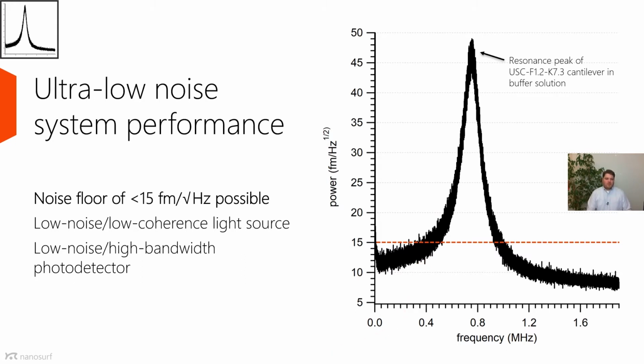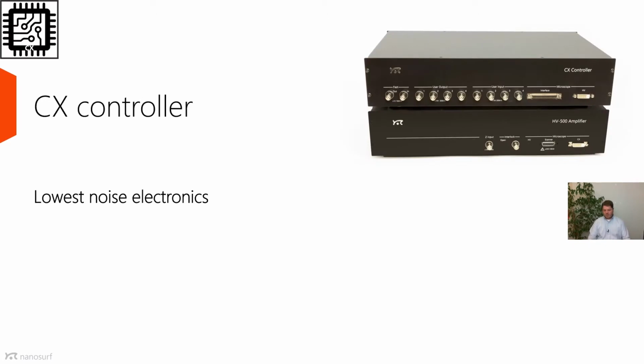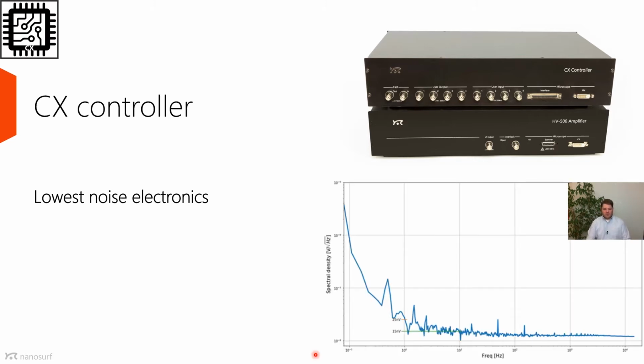So then, on top of this low noise light source and low noise detector, we also have to make sure that the signals that we get out of the scanhead, and that we process, are also low in noise. And we created the CX controller, which you see up here. And actually, this is one of the lowest noise, or it's the lowest noise controller currently that we know of. We have noise floors at 1 Hertz frequency of 25 nanovolts per square root Hertz, which is excellent. And if we go to higher frequencies, it's even below 50 nanovolts per square root Hertz. So it means we have an excellent and low noise controller to read our signals, but also to drive our instrument.